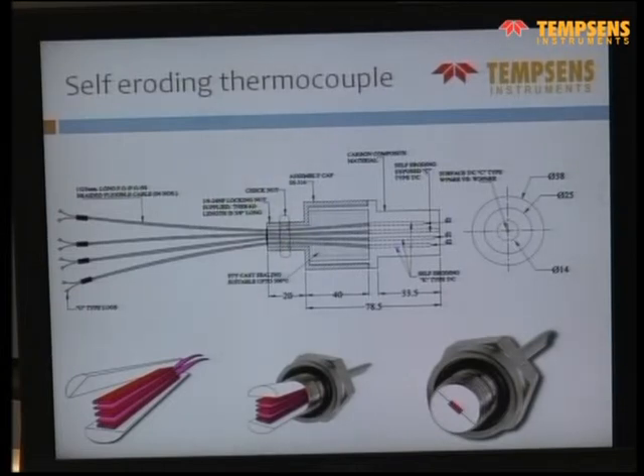So even when the strip is burning off, there is still more material coming out from the bottom, making the thermocouple itself, because these are very thin foils which, even when they burn, would make contact at some of the other places.